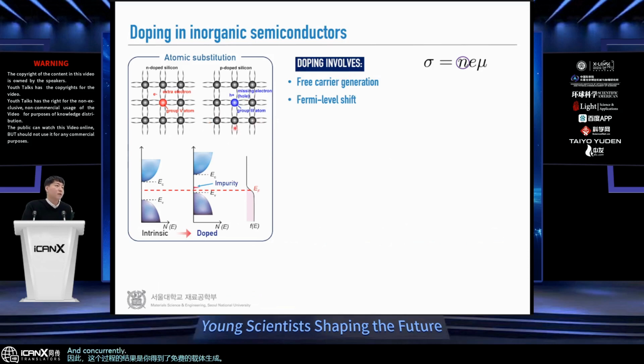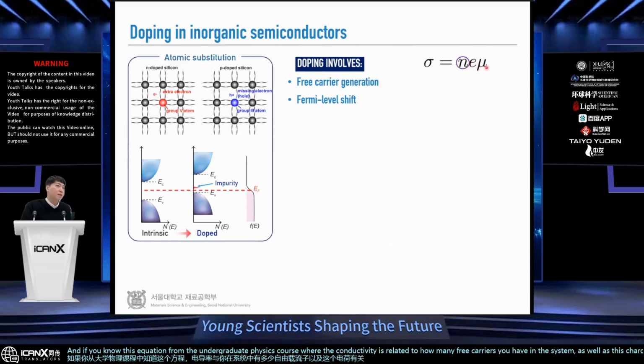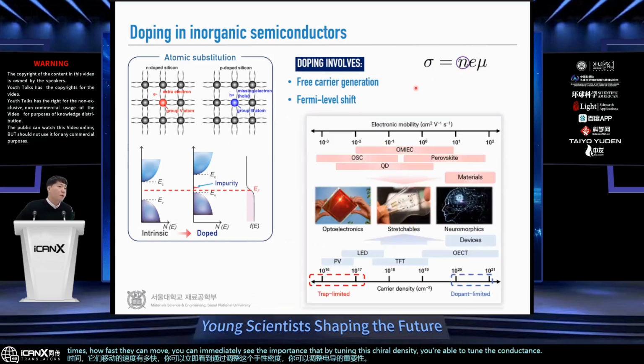Concurrently, in terms of the electronic structure, you create impurity states that can be ionized to give you a free charge carrier concentration. Therefore, this results in the Fermi level shift. And if you know this equation from the undergraduate physics course, where the conductivity is related to how many free carriers you have in the system, as well as this charge times how fast they can move, you can immediately see the importance that by tuning the carrier density, you're able to tune the conductivity as well.